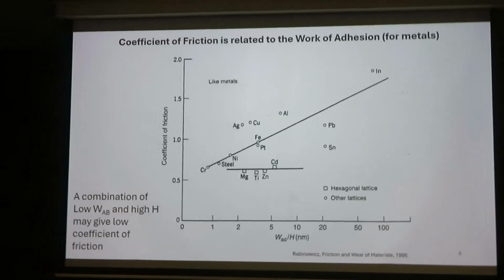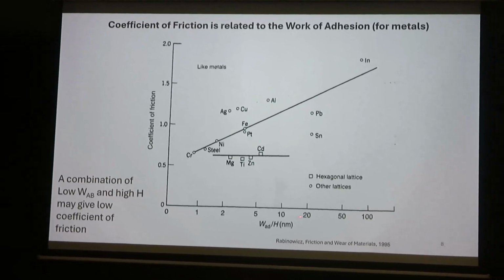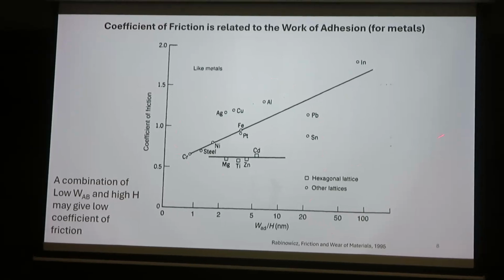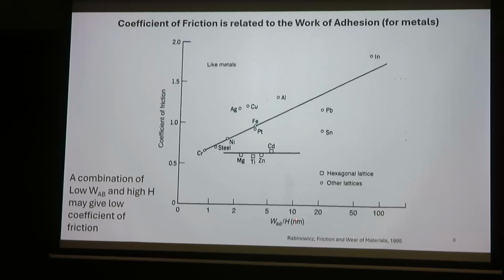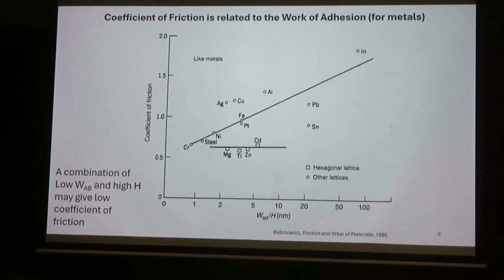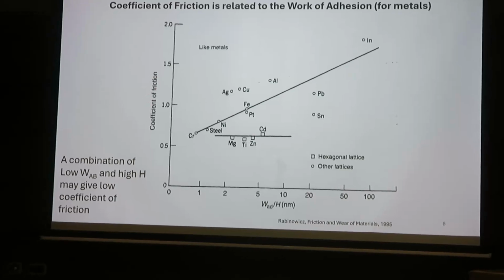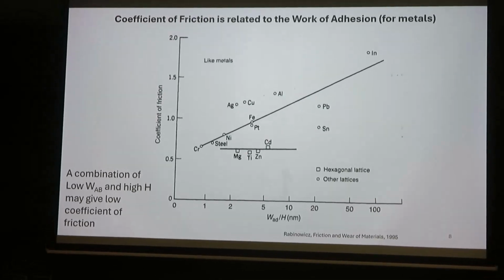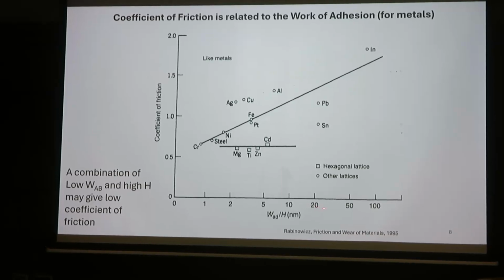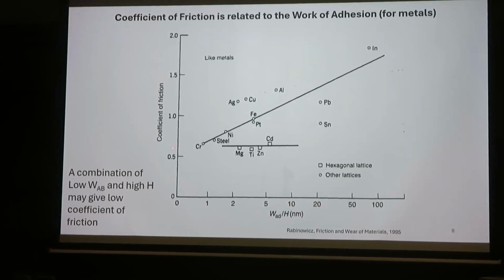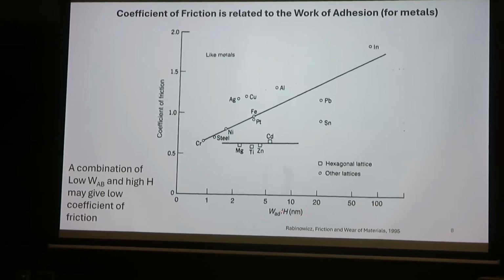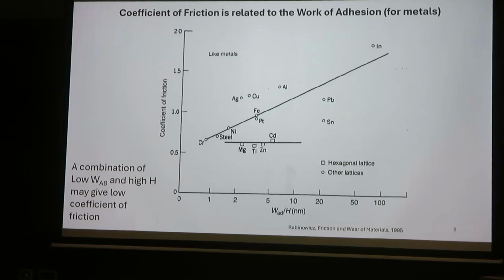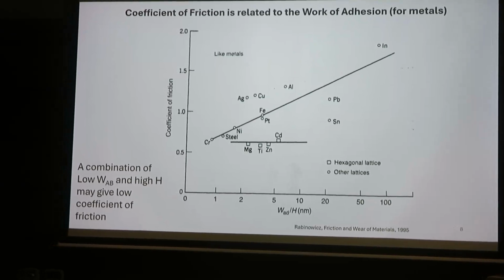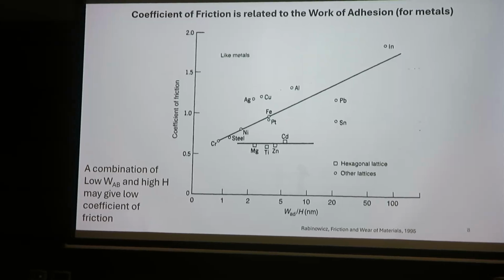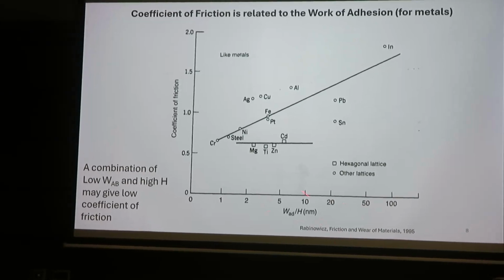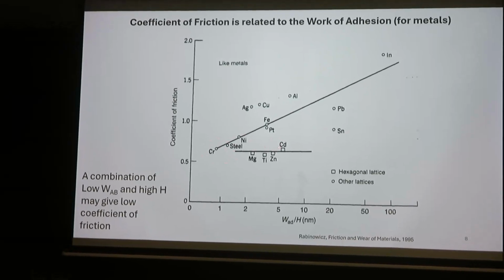In fact, long back in 1995, Rabinowicz had given this graph in his book, where he has plotted the work of adhesion divided by hardness, this ratio, as a function of coefficient of friction for metals. So in those days, mostly he was working on metals. What this says is that the coefficient of friction is low if this ratio is low. So that means a material should have low work of adhesion and it should have high hardness. This combination has to be there. If you have this combination, then you end up with low coefficient of friction here.